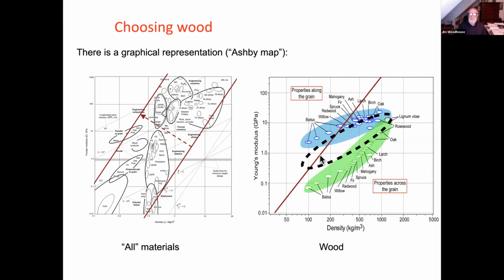One can make an argument that this is probably the least bad version of the criterion, shall we say. It is taking account, up to a point, of both the long grain and cross grain. So it still slopes down. This one had a slope of roughly 1, this one had a slope of roughly 3. This one is halfway in between on the log scale, so it has a slope of 2.